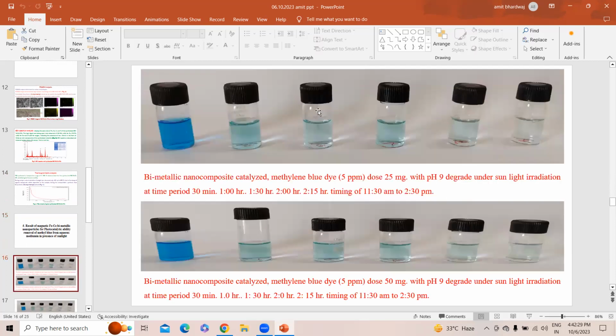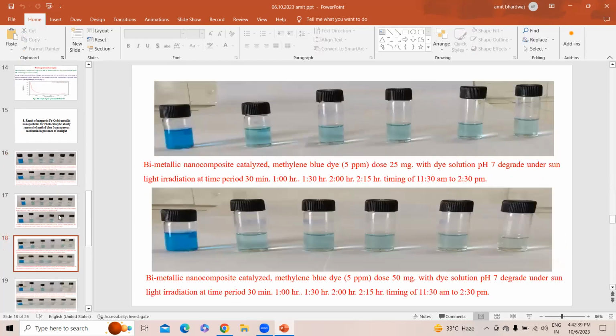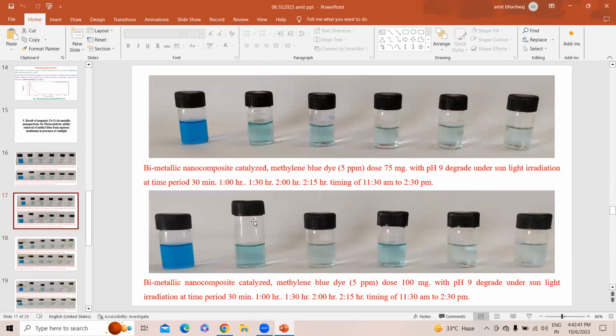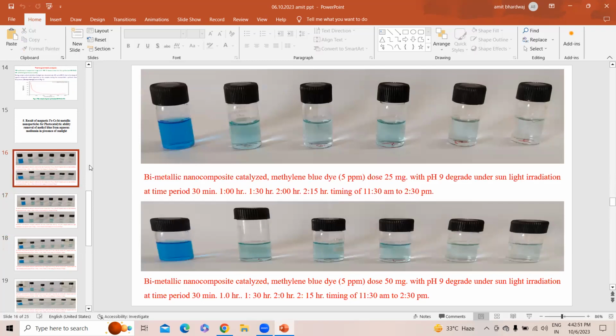With the bimetallic nanoparticles, I prepared a sample of 5 ppm with pH maintained at 9, and the dose changed to 25, 50, 75, and 100. The concentration of dye and pH are constant, with different doses of nanoparticles. You can see the degradation of dye at different stages: 30 minutes, 60 minutes, 90 minutes, 120 minutes, and 135 minutes.